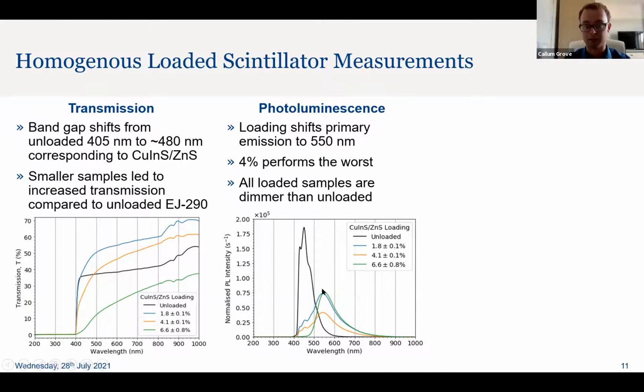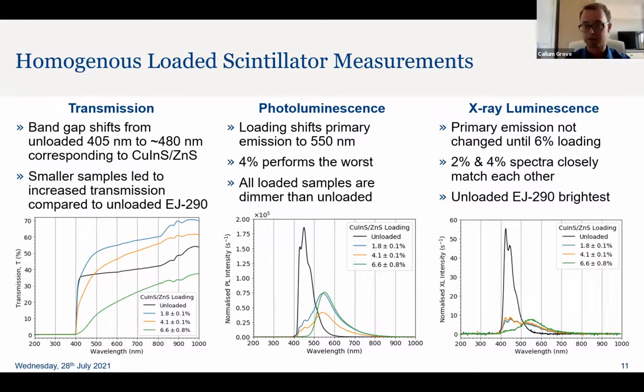However, as I said, the intensities themselves dropped off dramatically for the homogeneously loaded, and so we think that the benefit of loading homogeneously is not as high as having an unloaded scintillator, and that's why we went for the sedimented with a highly concentrated layer. A similar story is seen with X-ray luminescence. The unloaded plastic peaks have dropped in intensity, and there's a shift towards the quantum dots, but there's even less of a shift.